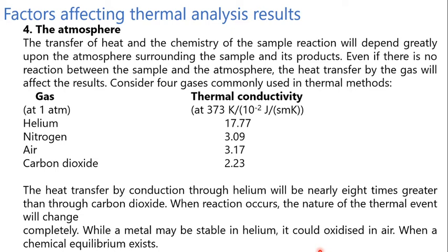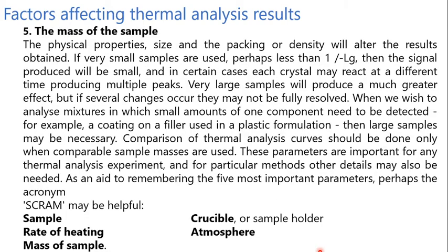The heat transfer by conduction through helium will be nearly 8 times greater than through carbon dioxide. When a reaction occurs, the nature of the thermal event will change completely. While a metal may be stable in helium, it could be oxidized in air when a chemical equilibrium exists.